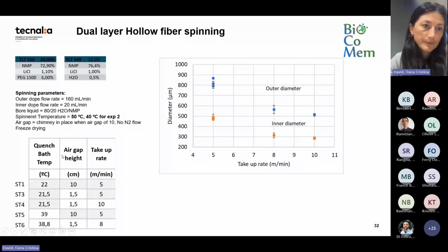First of all, we change the temperature in the bath. We made 3 experiments at 20 degrees temperature in the coagulation bath and 2 other experiments at 40 degrees. And then we check air gaps of 10 and 1.5 centimeters and take-up rates of 5, 10, and 8. Dimensionally, we can see that both the outer and the inner diameter obviously decrease with increasing take-up rate, and it doesn't matter at which air gap height you work and at which quench bath temperature.